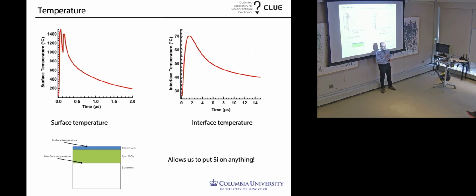And there's an important trick to it, which I think can be credited to your group, which is before you deposit the amorphous silicon, to put down a layer of something that can withstand high temperatures. So we normally use silicon dioxide. So you deposit silicon dioxide, you deposit amorphous silicon, that can all be done in one go. Then we hit it with a very short pulse laser. And that short pulse laser heats up the surface, melts the silicon, and then the silicon cools, and it forms this polycrystalline structure, which makes extremely good transistors.